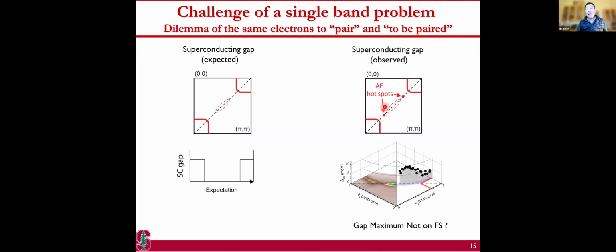Basically, if I measure the gap along the underlying Fermi surface, naively I would say the gap should be maximum along this Fermi surface. And as I'll show you, the maximum is not along this Fermi surface. There is a gap, there is superconductivity, but the maximum is where there is no reconstructed Fermi surface. This clearly, as you will see, also ties into the mystery of the pseudogap.